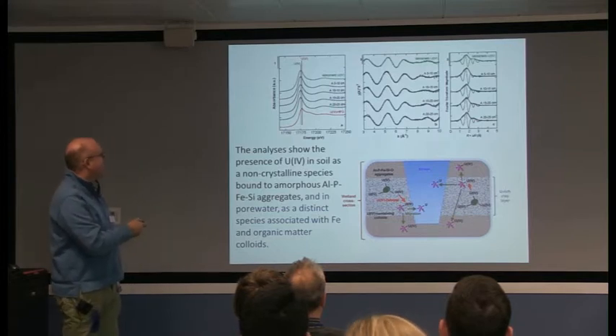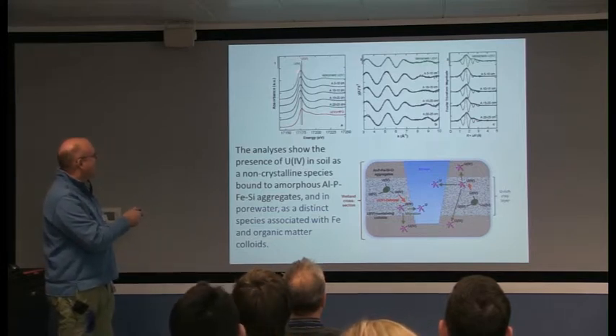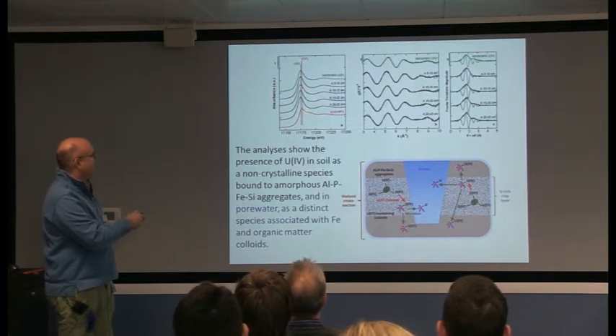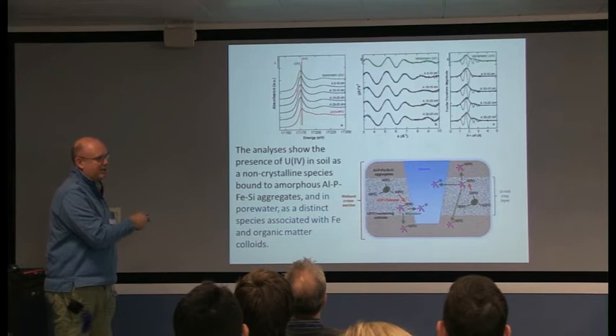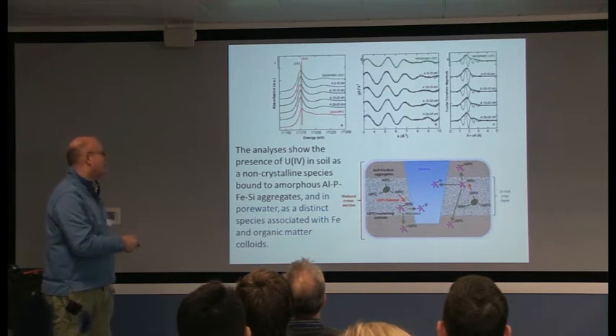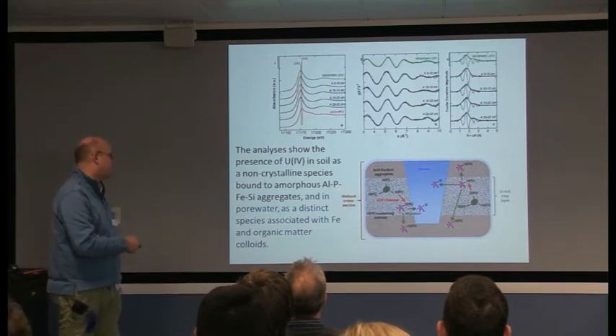Here are the zones—this is a uranium-4 standard, this is a uranium-6 standard, and you can see that all the uranium seems to lie under the uranium-4, so it is reduced, and it fits to an aluminium phosphate sort of environment.